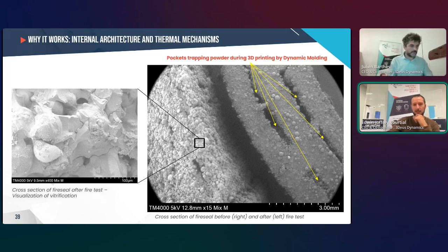silicon phase. This transition from a flexible composite to a semi-ceramic protective skin is what makes the architecture unique. During normal operation, the joint remains soft and compliant under flame exposure. It's self-organized into a rigid insulated barrier. Such a reversible behavior, flexibility in service and protection under fire, is directly enabled by the control of microstructure during